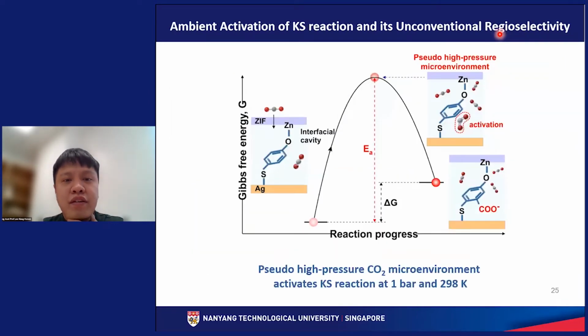Okay, so what is the driving force behind the activation of the KS reaction even at ambient operating conditions? So this again can be attributed to our pseudo high pressure microenvironment. So the presence of CO2 very close to our substrate will force them to interact and therefore activate KS reactions even at 1 atmospheric pressure and 298 Kelvin.